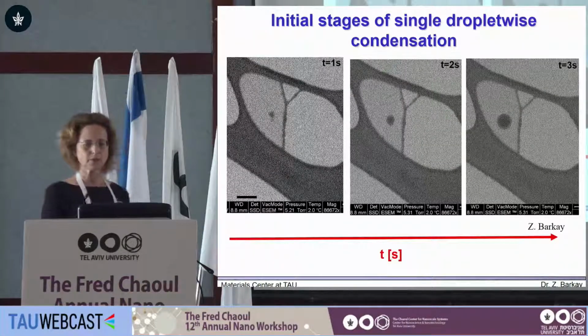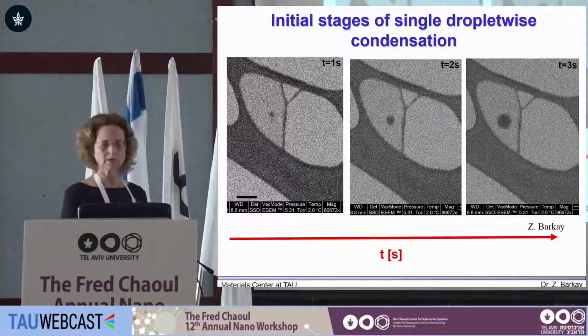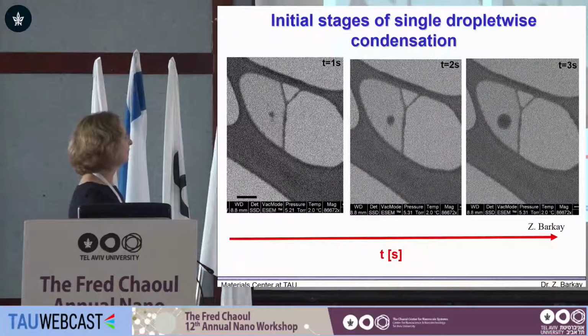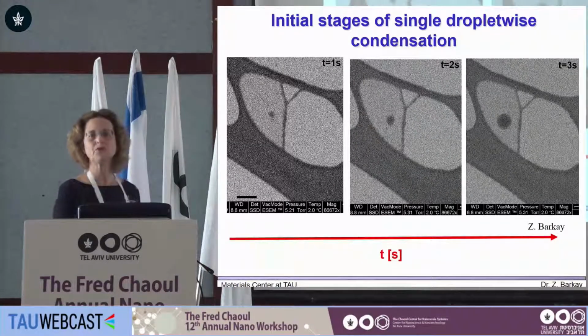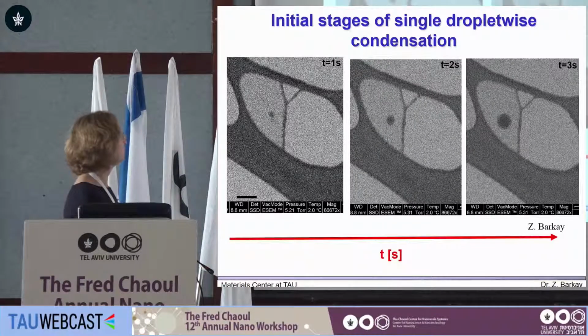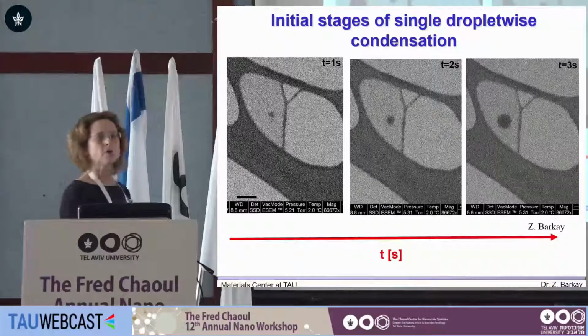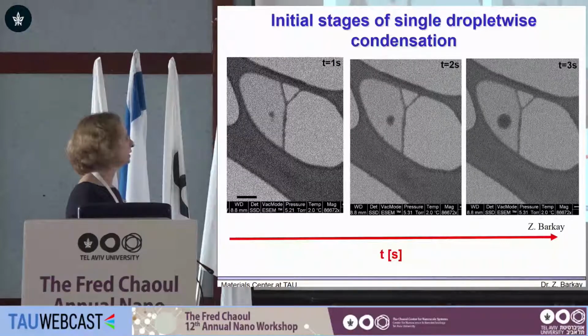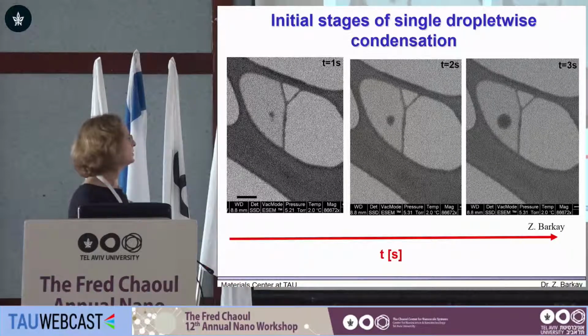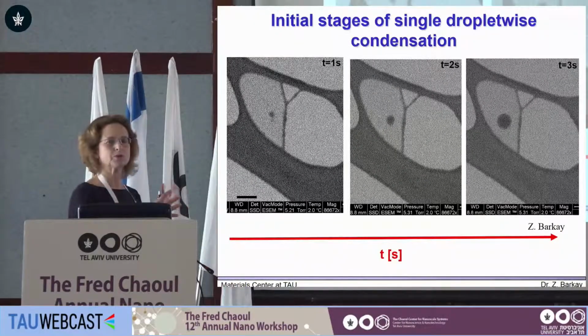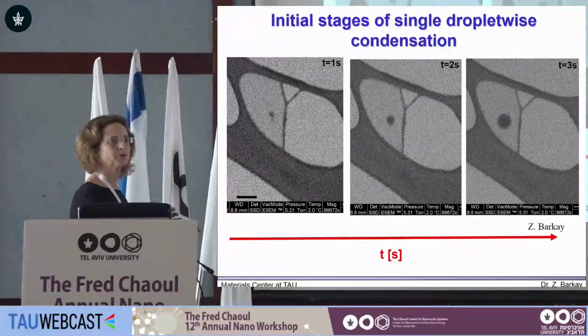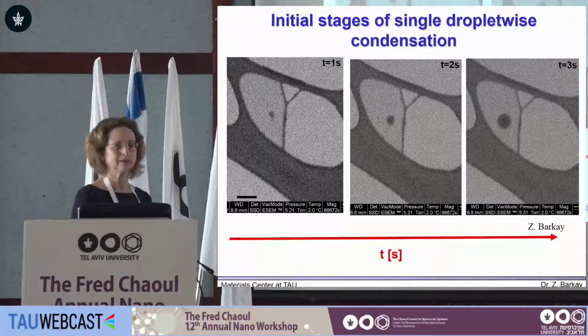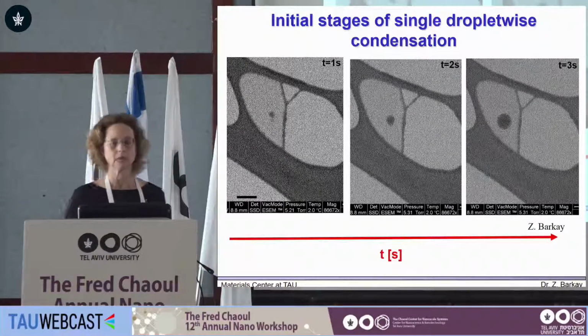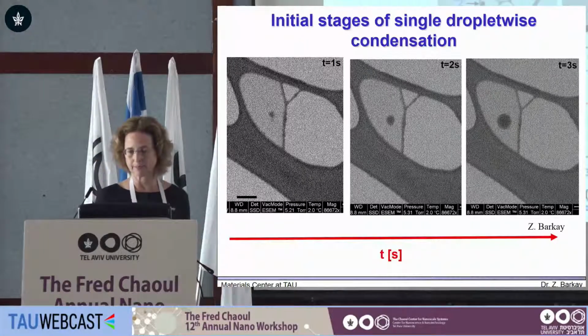Second procedure is for single droplet condensation, and these are the first seconds of the condensation on the film. This size was software measured to be 10 nanometers. In the initial state, the vapor is not very well organized, but after a few seconds, we have this circular arrangement, which is the more equilibrium arrangement that we are familiar with.